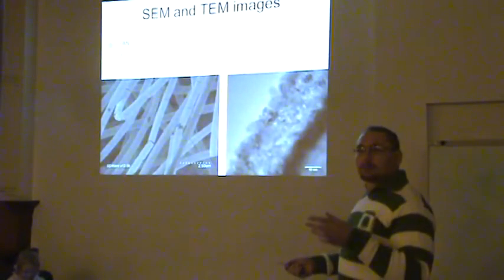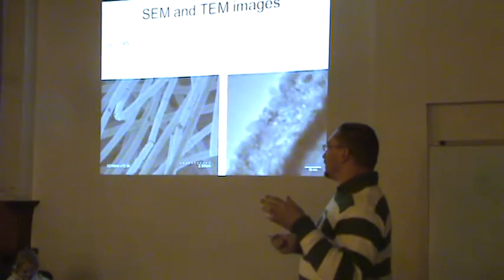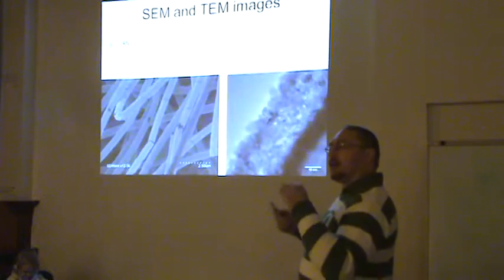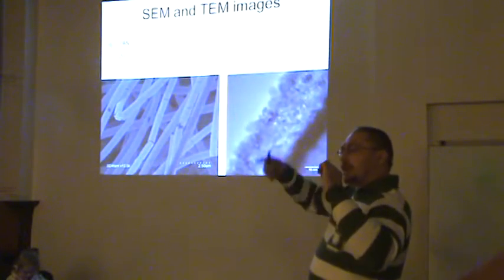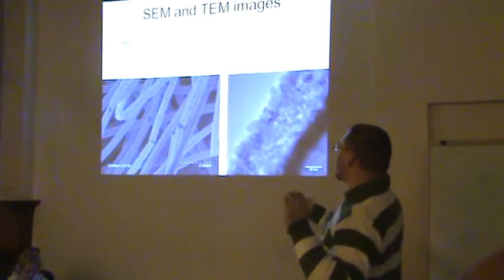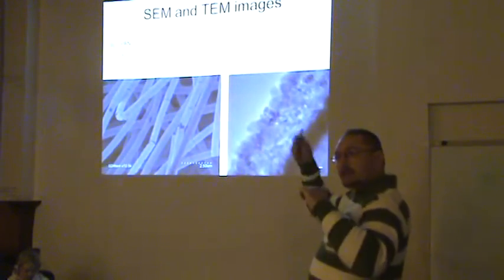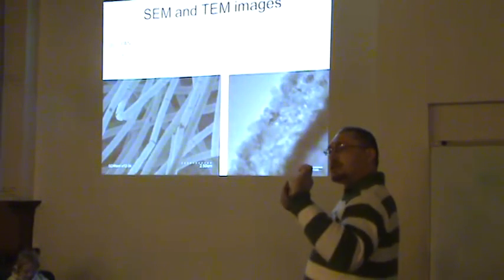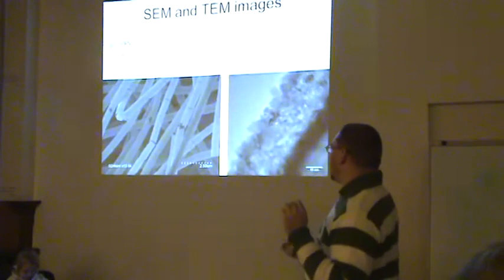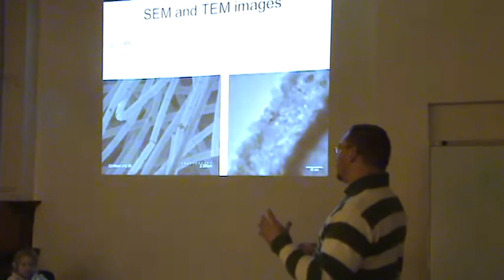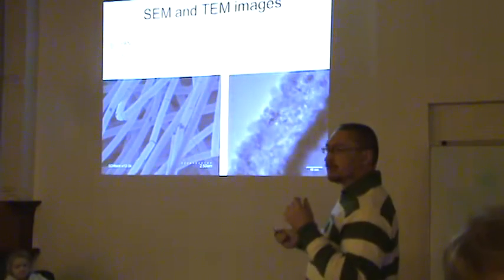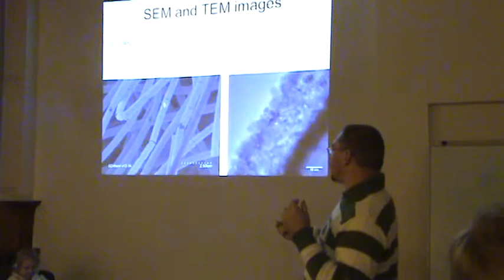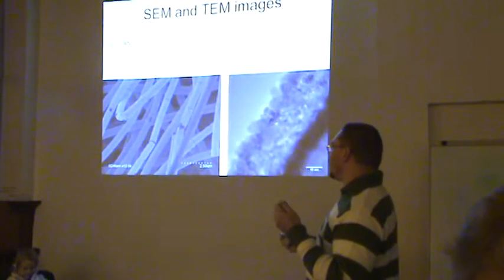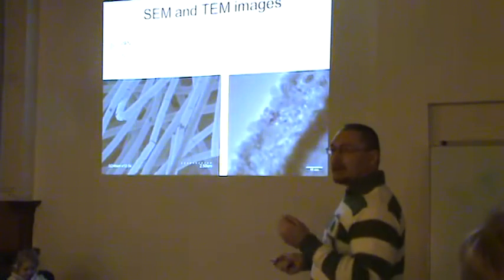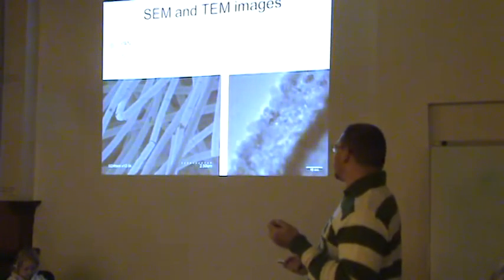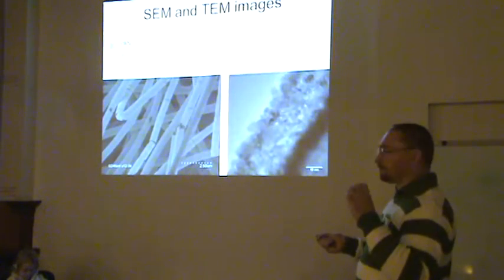So this is an example of what we normally have measured. This is an image of an organic nanowire, which is coated with a thin layer of zinc oxide. So the core is organic, and then you have a thin nano layer on this nanowire. If you take a look at these samples and investigate them with SEM, you will see that these nanowires have a diameter of about 300 nanometers, and the length of these nanowires is about 1 micrometer. This is what we managed to do with SEM.